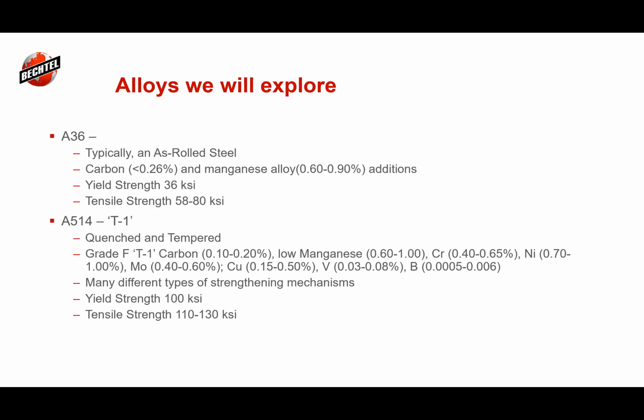The A514, oftentimes we call it the T1 type steels. Those that we're going to talk about are all quenched and tempered. So a different manufacturing process in the sense that they are raised up, quenched, and then tempered to have a nice tempered martensite. They have a lot going on because if you look at the alloys, they have carbon and they have manganese. I use the grade F as an example, but they also have chromium at a healthy amount,